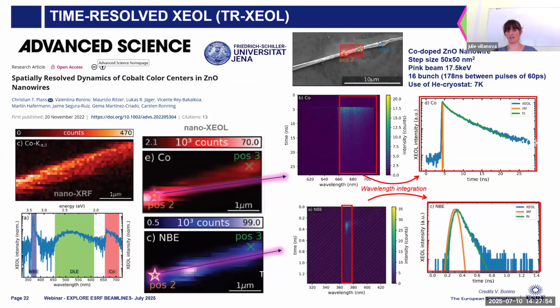And in this present study, what they have found is that for the cobalt luminescence, there is a new recombination mechanism, because we can actually decorrelate this into a two-component decay, a fast decay first and then a slow decay. And the fast one is attributed to the direct ionization of the cobalt color center by the X-rays.